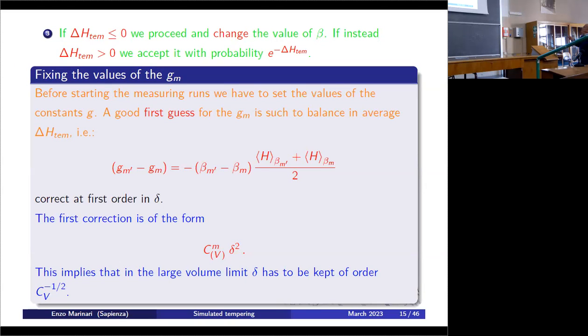And now look up there. As before, if delta H is smaller than 0, you change the value of beta. So you say that the system is going to the new value of beta. If delta H is larger than 0, you accept with the Metropolis approach with probability e to the minus delta H. I didn't tell you much about how to fix the value of G. Again, ideal, as we said, would be to fix them to beta times the free energy density, but you cannot do that because you don't know the free energy density, or you already would have solved the problem.